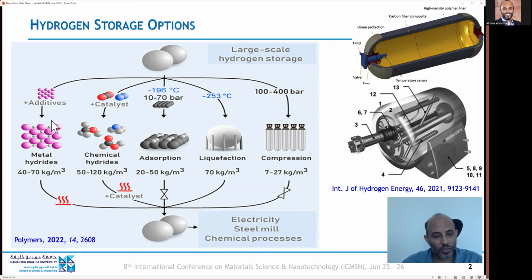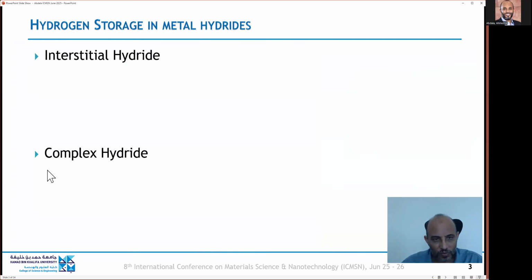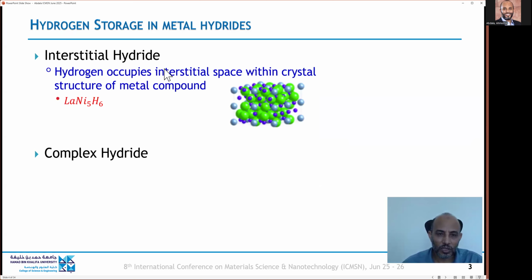Alternatively, we can use metal hydride. So this would be a metallic crystalline material where hydrogen can be stored either as an interstitial in the cavity of these crystals, or it can form intermetallic compounds. There are two different types of metal hydride, depending on the mechanism by which hydrogen interacts with the metal atoms. One is an interstitial hydride, where we have a metal crystal and the hydrogen sits in the interstitial cavities of that crystal metal structure. An example of that is lanthanum nickel hydride.